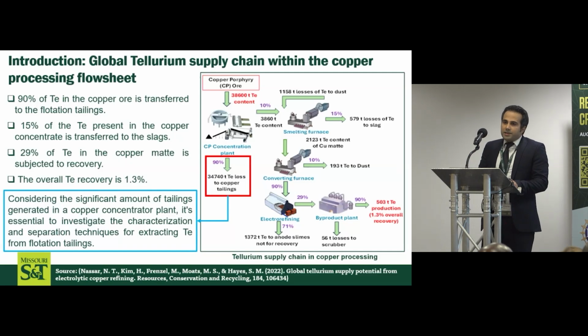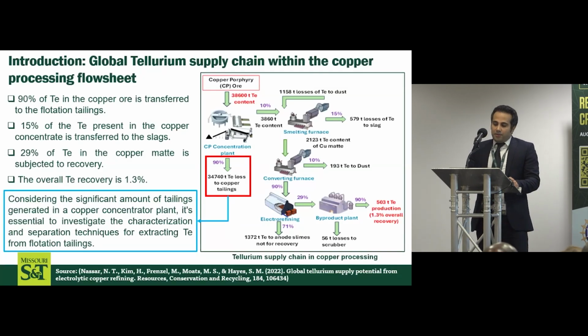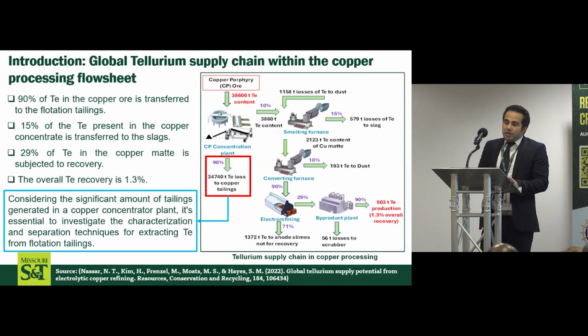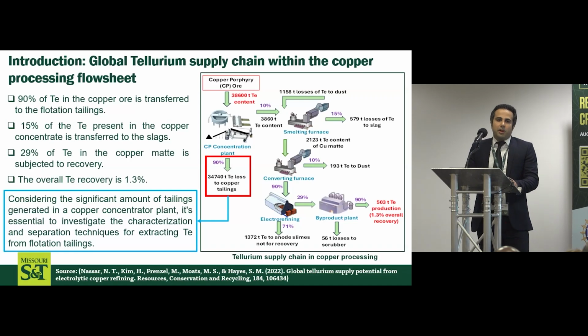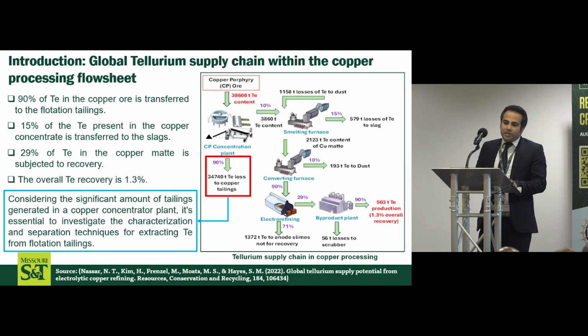Ore extracted from the mine is transferred to the mineral processing plant to produce copper concentrate. The concentrate is then smelted to convert to copper matte. The copper matte is then purified in the converting furnace, anode casting, and electrorefining process to produce copper cathode. In this flow sheet, it's estimated 40,000 tons of tellurium are extracted from the copper mine. However, only 10% of this tellurium is transferred to the concentrate. The remaining 90%, equal to 35,000 tons of tellurium, is transferred to tailings. Considering the significant amount of tailings generated in copper processing plants, it's essential to investigate the characterization and separation techniques for extracting tellurium from flotation tailings.